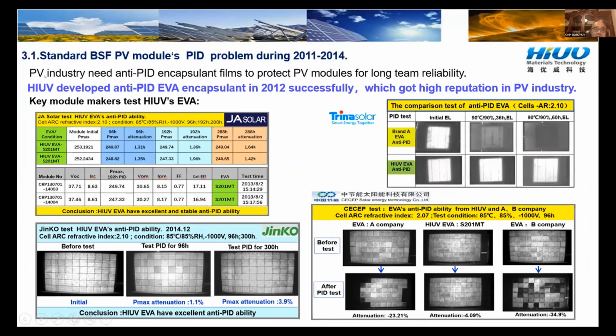So after we successfully developed anti-PID EVA, a lot of module makers tested our material compared with others. This is JA Solar. We tested our material with triple the testing time. They can use almost 300 hours to test. We still got a really nice result, with power drop of less than 2 percent.